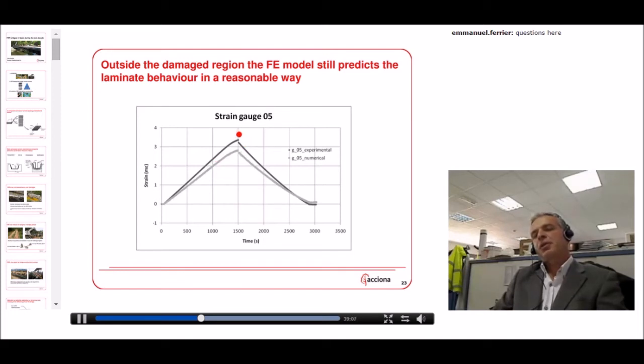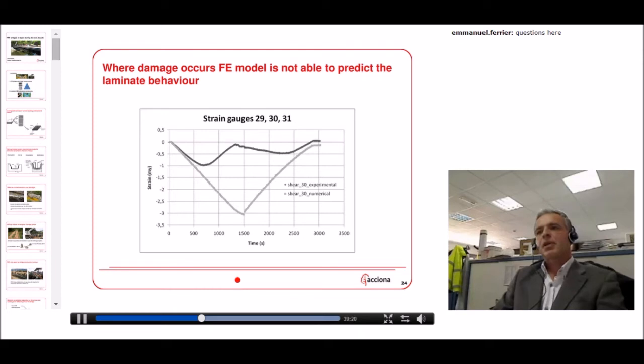The strain gauge at midspan, at the bottom of the girder, you can see there is still a good agreement between the numerical and experimental values. But if you look at the strains close to the abutment, you see that the numerical model is not able to represent the physical behavior of the laminate. And this is obvious because the model we use is an elastic model, and the failure was localized close to one of the supports. So in this area, the model is not able to capture the actual behavior of the girders.